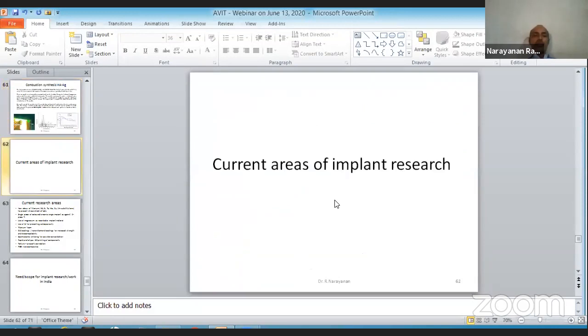So why I'm talking about all this is because we started from metals, titanium, and we went on to production of alpha plus beta titanium 6. We can modify the metal itself, and in case the properties are not good enough for fitment inside the body, you can also modify the surface, with respect to improvement of surface roughness or surface chemistry, chemical state, or biological state. So in this regard, we dealt with anodization and cathodic hydroxyapatite, and with the view of improving the hydroxyapatite and supplementing it with different ions like strontium or silver, coatings have been produced. So this is basically an evolution of body implants.